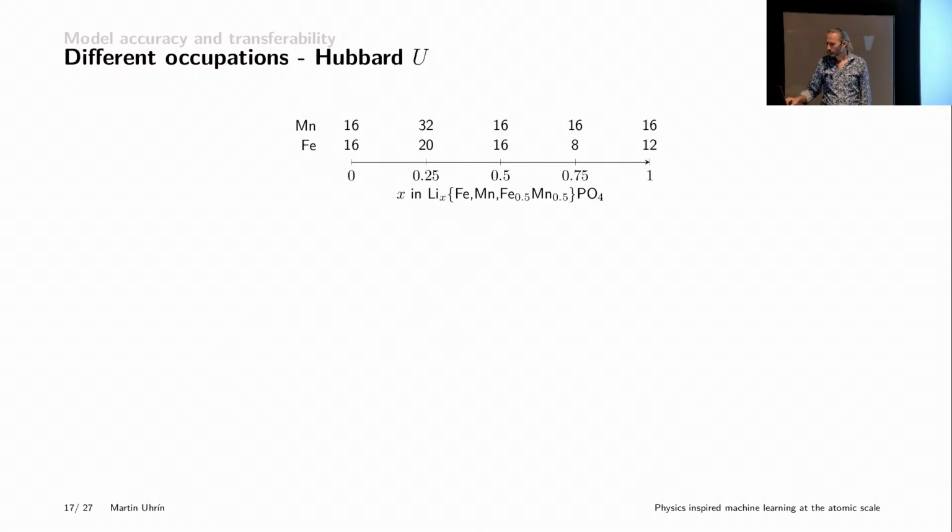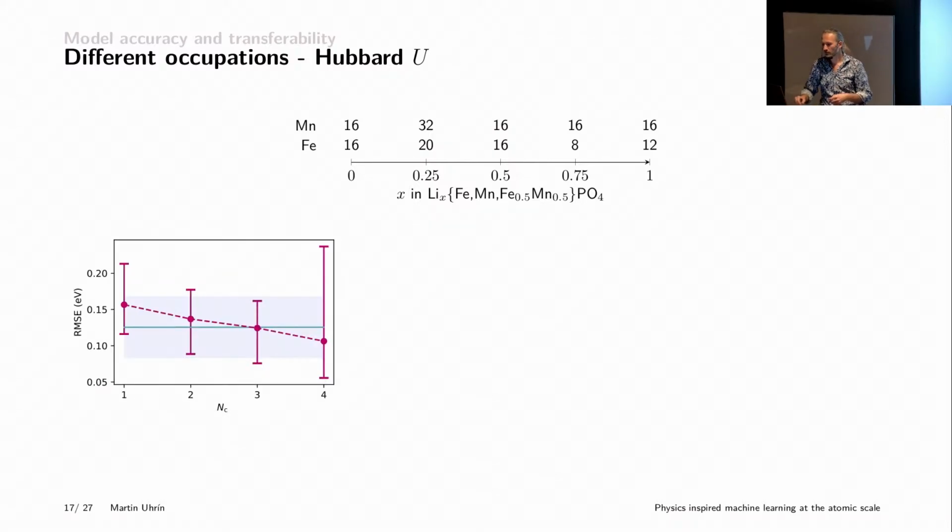This one I think I'll skip, but I wanted to just show you one thing that seems to be a property of these equivariant models, which is that they can transfer quite well to systems that they haven't seen, or at least configurations they haven't seen. So here I'm going to take those olivines, and as I said to you, there are different amounts of lithium that I can add to these, right? So what I'm going to do is train the model on this one and ask it to predict all of the rest of them and see how well it does. So this is really trying to predict the different oxidation states that it hasn't seen before. And then this one and all the others and all possible permutations. Then I'm going to train on 2, and then all possible permutations of the others, and so on.